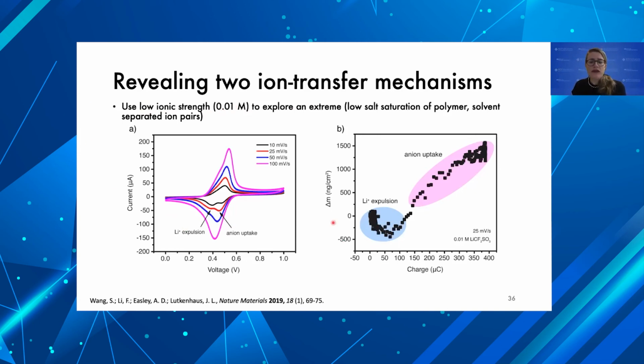So when we do that, we can clearly see a region of lithium expulsion associated with this first peak. To take you through this, this graph represents oxidation, where we go from a low potential to a high potential. On the x-axis, this is the current we measured, but we've integrated it so that it represents Q. As we start to oxidize, the mass of the electrode actually goes down as we're expelling lithium cations, and then it increases as the anions come in.